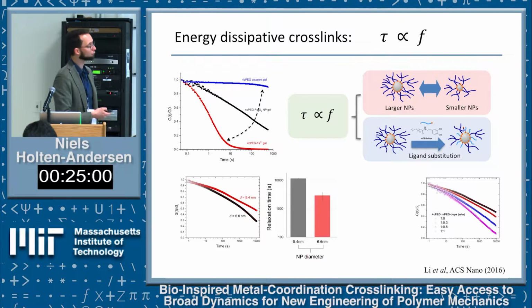A very easy trick is to just make smaller nanoparticles. We should have fewer ligands stuck per particle, so it should be more fluid-like. That's exactly what happens, as shown in this stress relaxation curve. The smaller the particle, the more fluid-like the network—it relaxes faster. This bar plot shows the same thing.